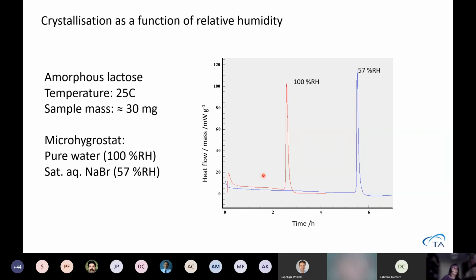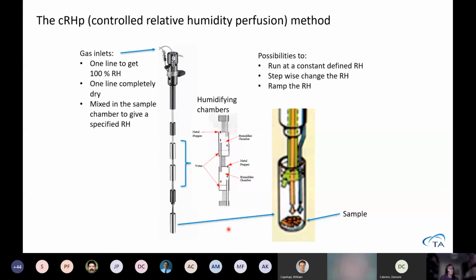So you can see how you can set the time to the peak by choosing the vapor activity. The bigger the sample, the longer it takes to absorb all the water. So you play with both humidity and sample size in this case. Then, what we just saw in the previous slide was a fixed relative humidity, but you can also change the relative humidity during the measurement.